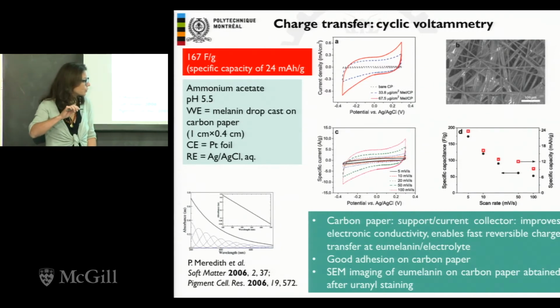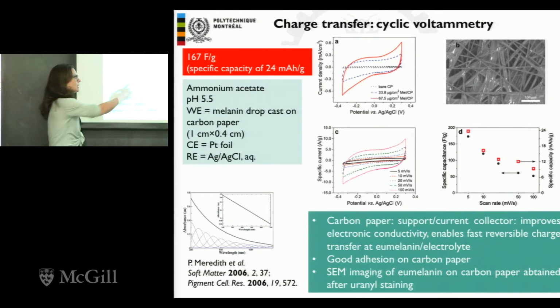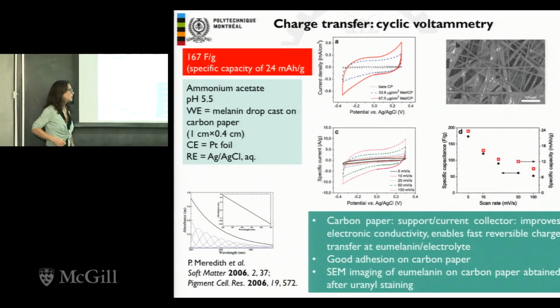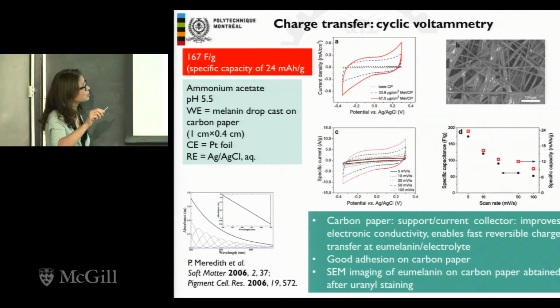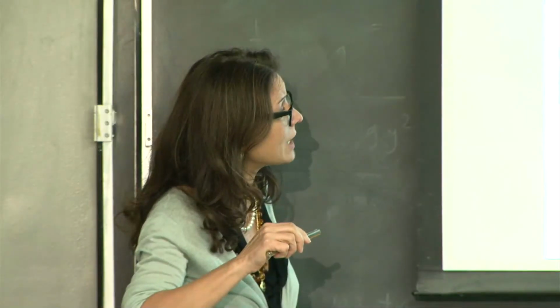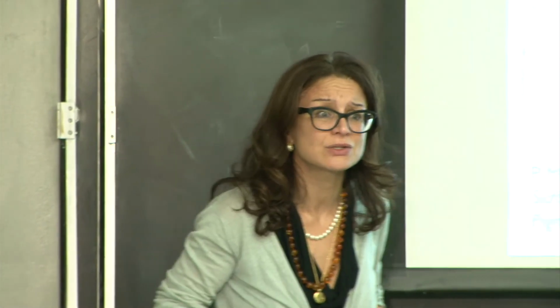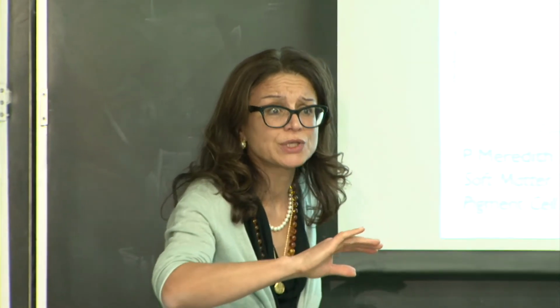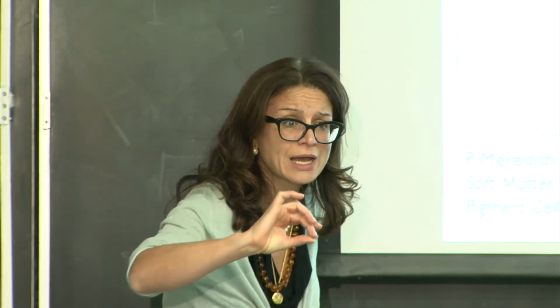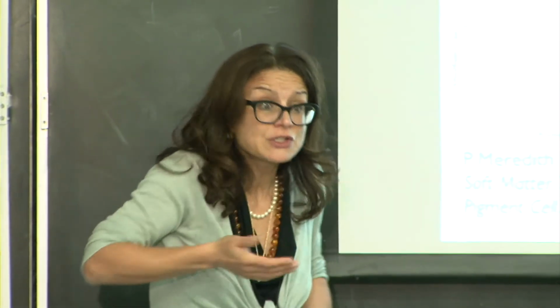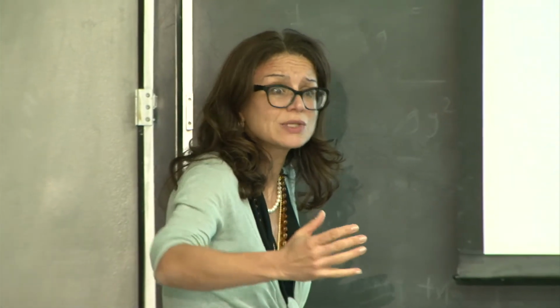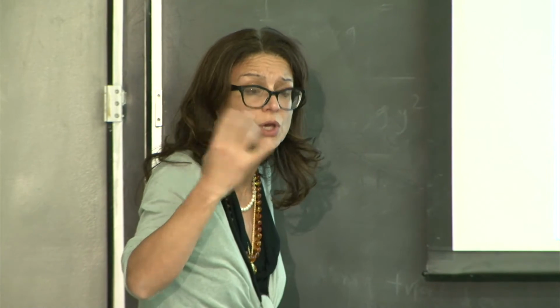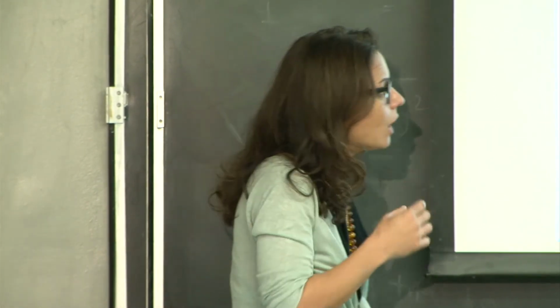One of the models that people invoked to explain this featureless spectrum has been the presence of a convolution of the absorption of different chromophores that at the end of the day results in this featureless spectrum. So kind of a chemical disorder model. And at the end of the day, I think we could really establish a parallel between the featureless voltammogram and the featureless optical spectrum, to say, hey, these are natural materials. They are not synthesized in the lab. So given their purity, the different polymerization sites for the two building blocks, we cannot pretend physical order, even in the supramolecular organization. So it's kind of intuitive that you have this kind of convolution behavior when you go to measure the physical properties.